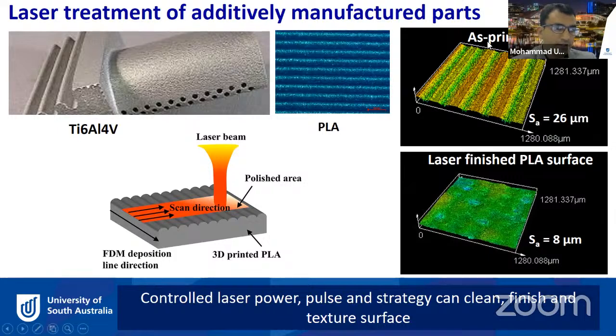So we have recently done these kind of experiments on a 3D printed PLA surface, and we found that this is the as-printed PLA surface, and after the laser finished, we found that surface roughness has dropped from 26 micron to 8 micron. So there are other benefits also you can have. Improving the other mechanical properties you can achieve by doing this laser surface treatment as well.